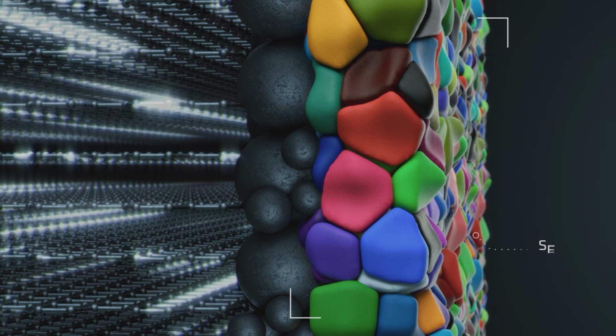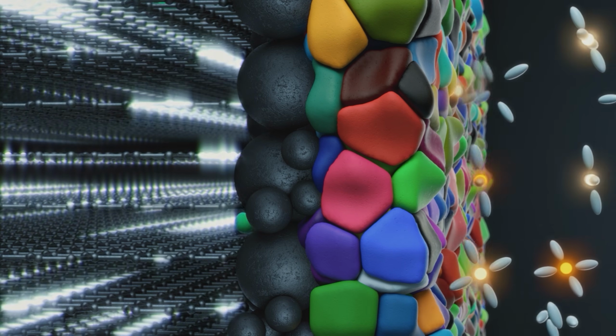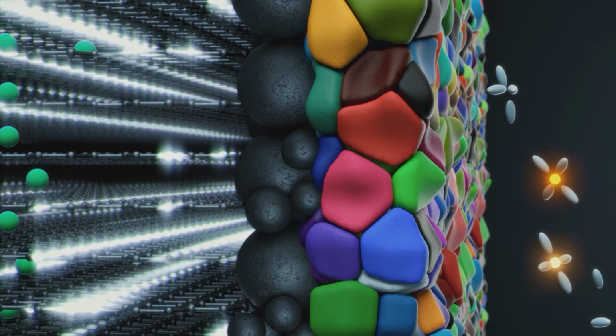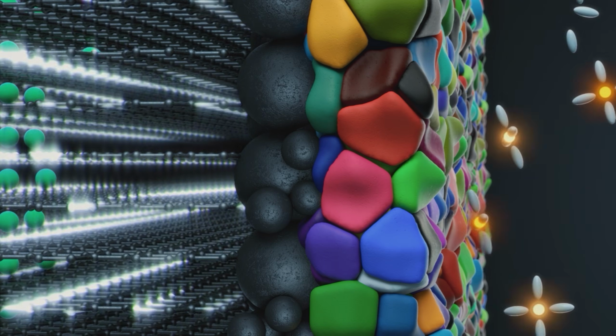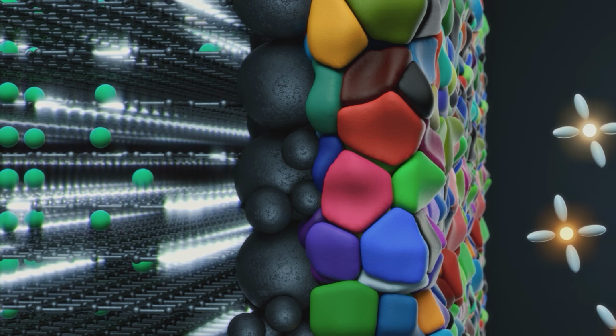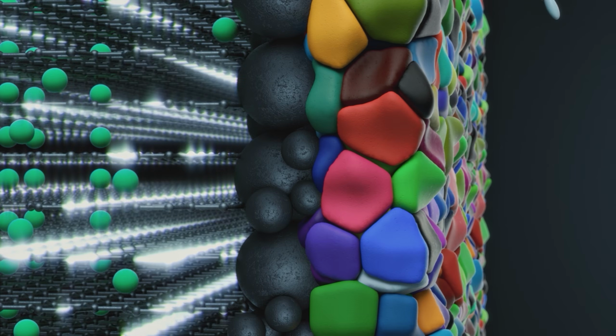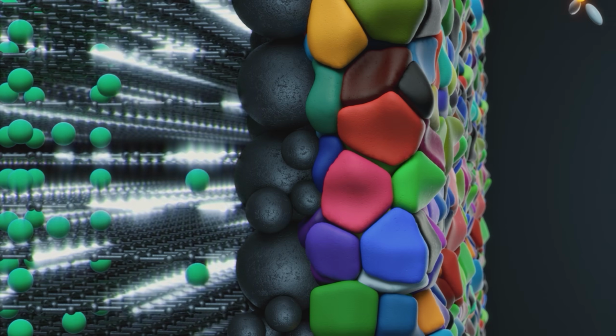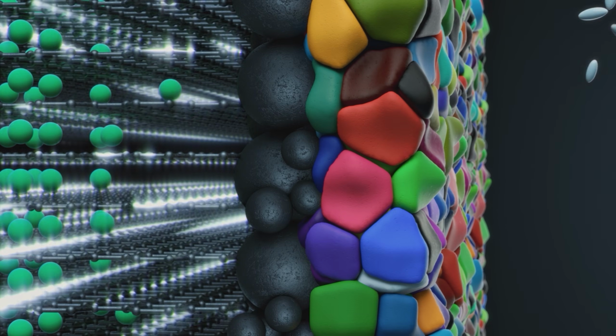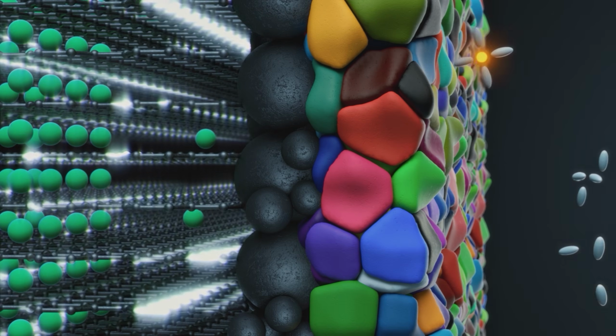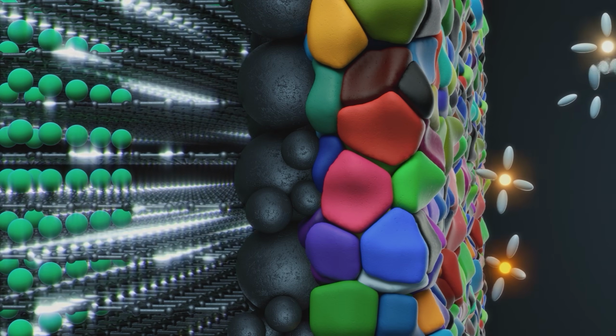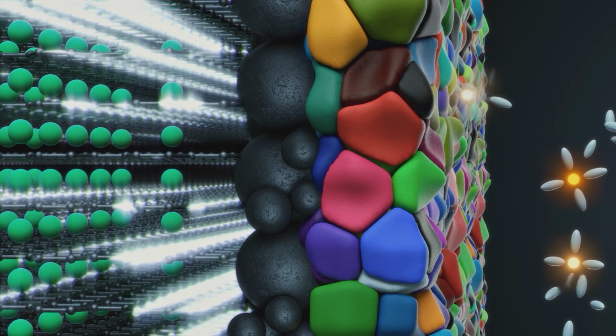A thinner SEI film should mean that the lithium ions can enter and exit the anode more easily. I'm not sure how CATL made the SEI thinner, but they most likely achieved that by tweaking the mixture of chemicals that make up the electrolyte solution. More on that in a moment. Either way, my guess is that the thin SEI is a minor contributor to Shenxing's charge speed.